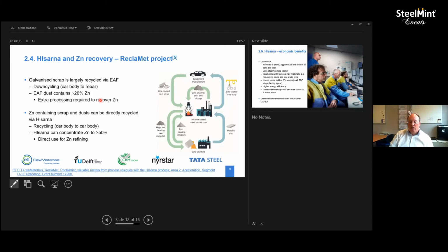But by recycling in HIsarna, what you can do is, because the temperatures in the process are so high, all the zinc evaporates, and we can concentrate the zinc in the final bag filter with the fine dust. And the aim is to make a zinc concentrate that has more than 50% zinc in it, which makes it suitable for direct use in zinc refining. So the intermediate stages can be skipped, all the pre-processing stages. And this is getting close to a prime ore for zinc. And that way we close the loop two ways. So A, you can recycle the very well-defined zinc-coated material back in integrated steel making, and at the same time you can recycle the zinc dust back to the zinc smelting industry, who can supply us with metallic zinc to make new zinc-coated steel.